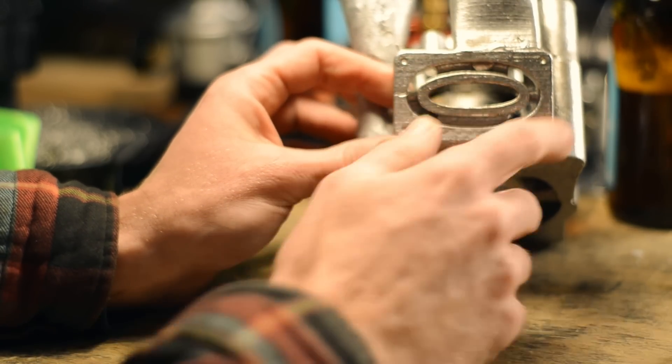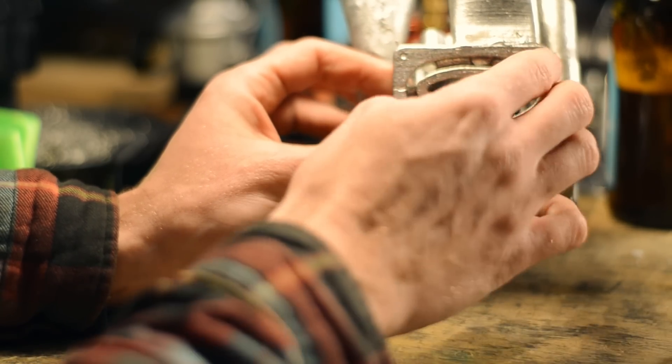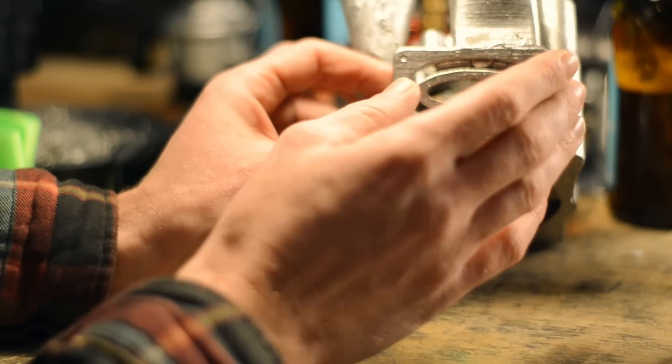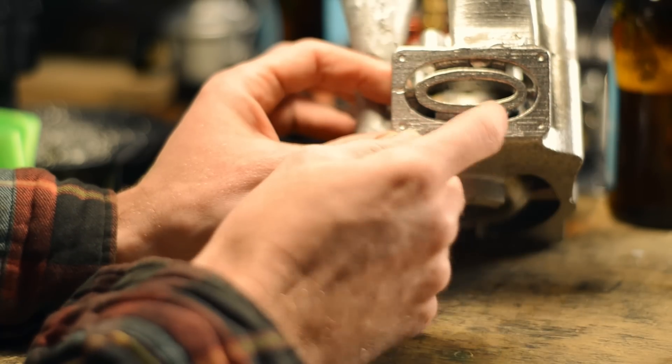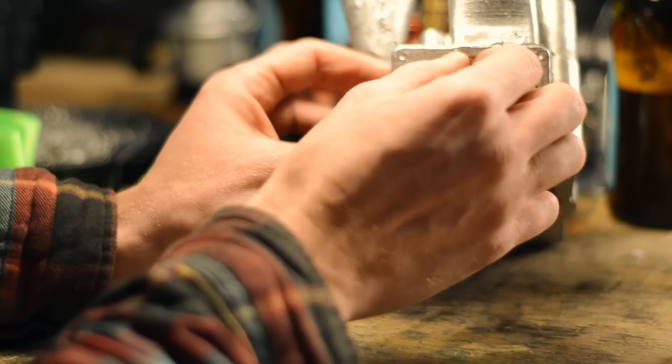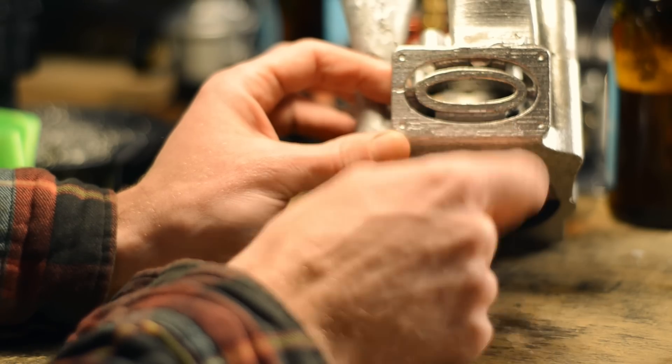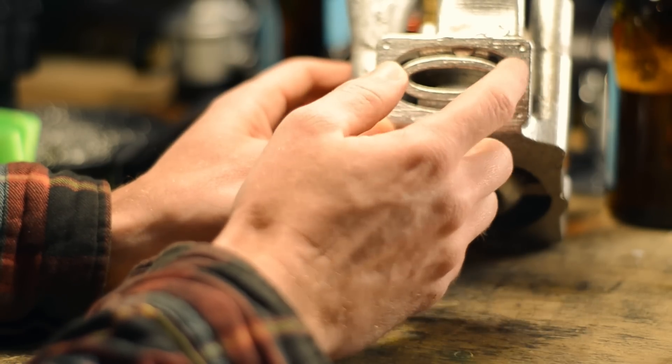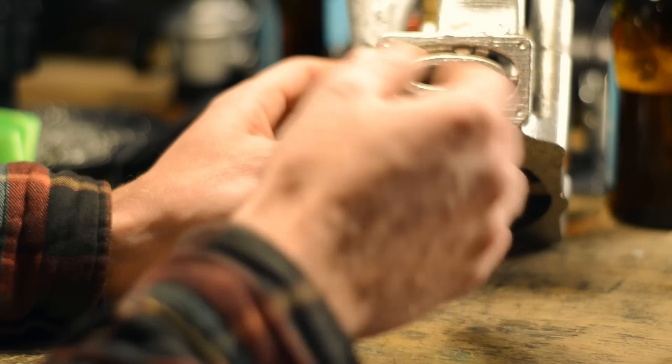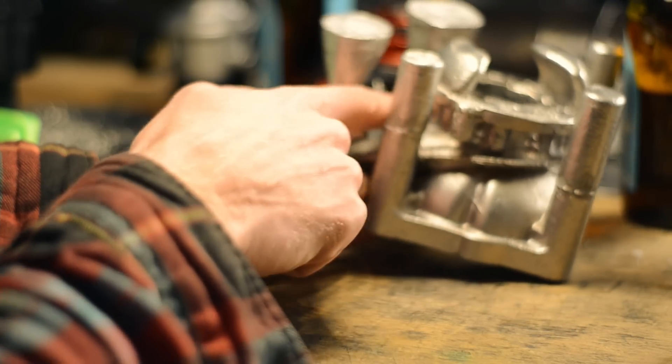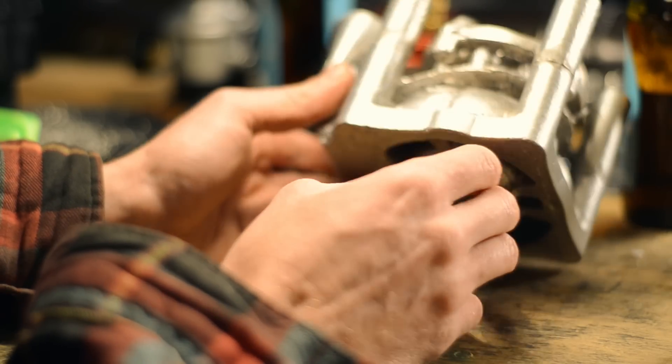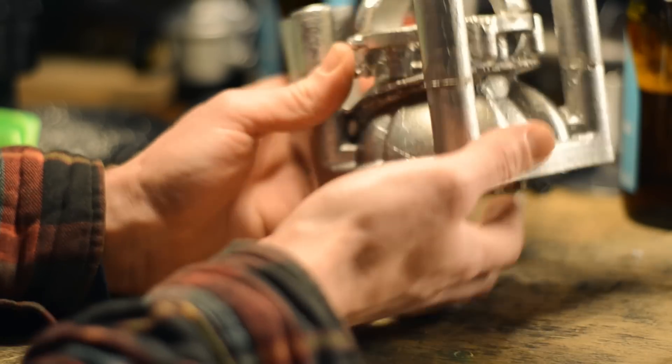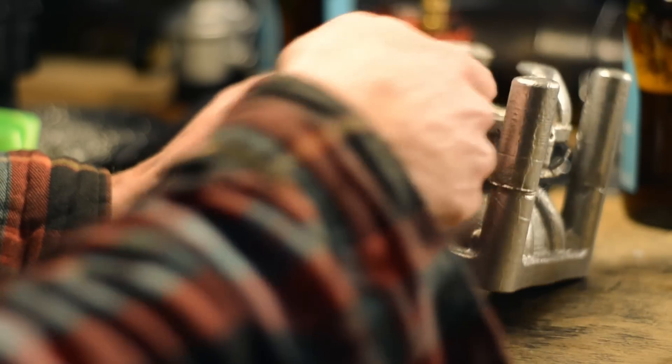So I made this flange with channels for water to flow in and up against the exhaust flange and around here and stuff. And there's two thin sections here and two thin but wider sections on the top and the bottom. And I think these thin sections caused a higher velocity in the metal stream and also a lot of turbulence when the metal was flowing up through the walls of the duct here and meeting up with the metal coming from the underside. And I think that's what caused the hole and all that porosity around this duct and around the exhaust.